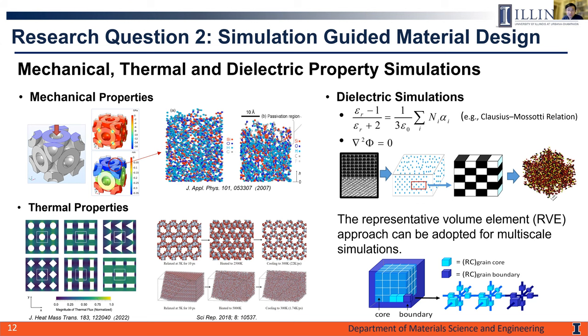To investigate the dielectric properties, we could use the effective medium theory to give a very quick approximation, such as the Clausius-Mossotti relation that is good for low-k porous materials. Alternatively, we could develop models to solve the 3D Laplace equation with the finite difference method, with material properties such as the polarizability for individual constitutive elements being determined by the atomic simulations, and then find out properties such as the dielectric constants. Here we could use representative volume elements, the RVE method, to link different scales of the computational models in predicting the material design.